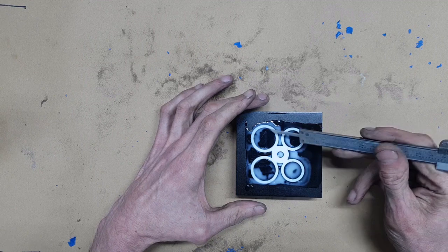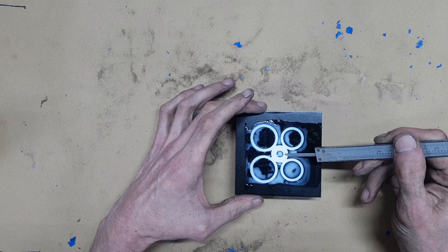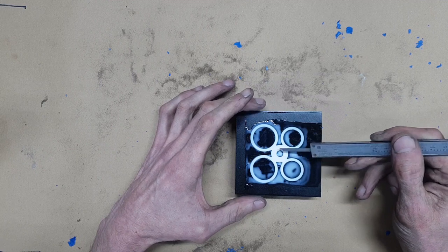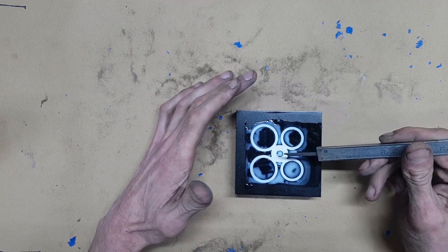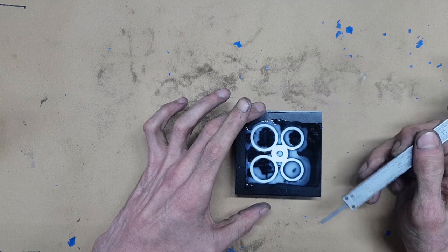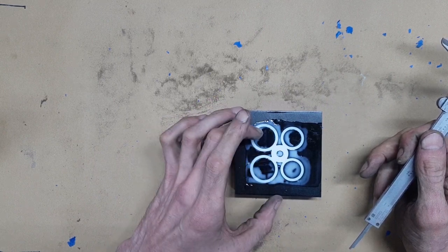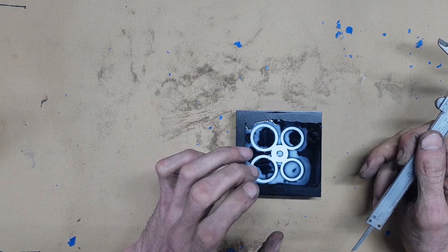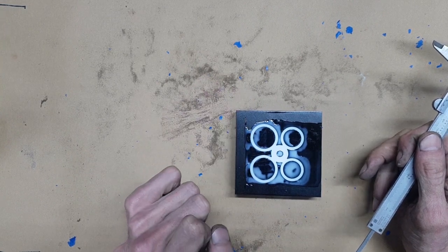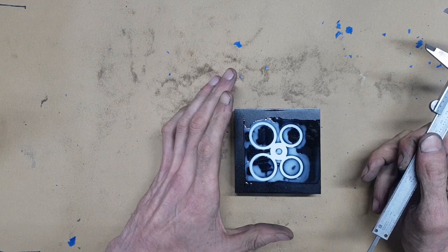So the more uniform mass, due to the smaller core here in the middle, due to the ability to be able to cast the small core finer in a finer powder, as said, and still be resilient for handling. That's a major breakthrough in modern Formula 1 engines, that you can handle the core, put it in, it's not going to move, and it's more precise, more supports the combustion chamber, and major.